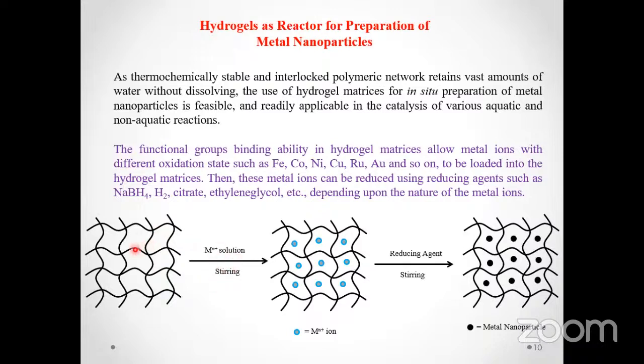For example, metal ions can be loaded into the hydrogel networks, as shown in this figure. In the first step, metal ions are loaded into the hydrogel network. And in the second step, those metal ions are reduced by using a suitable reducing agent, and that reduction of the metal ions results in the formation of metal nanoparticles. Then this hydrogel is converted into a composite or hybrid system which contains the polymeric network as well as the nanometallic part as well.